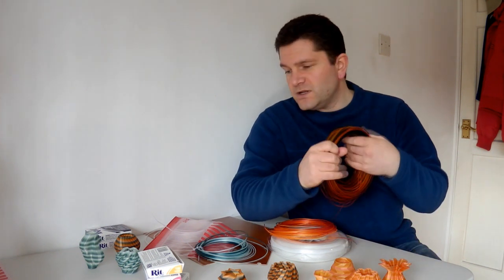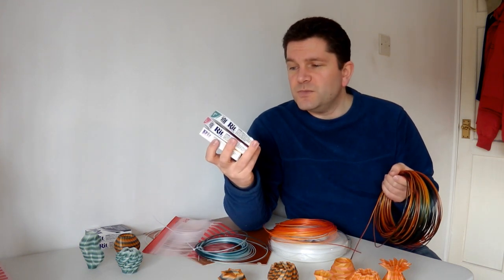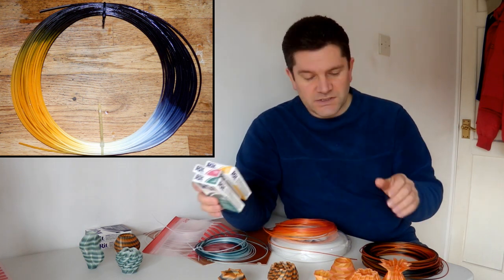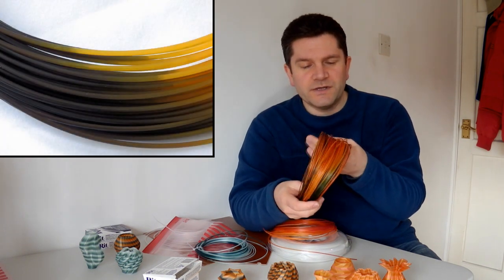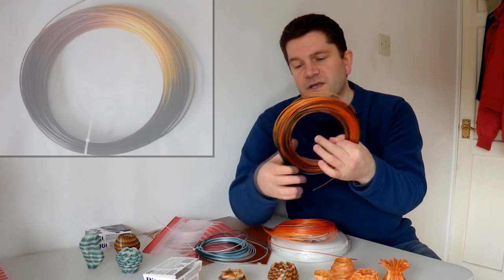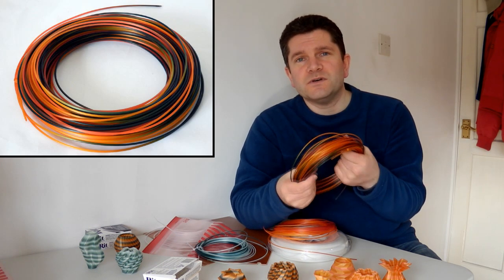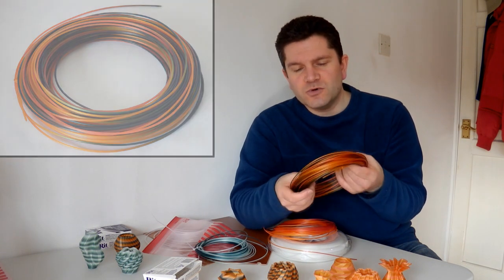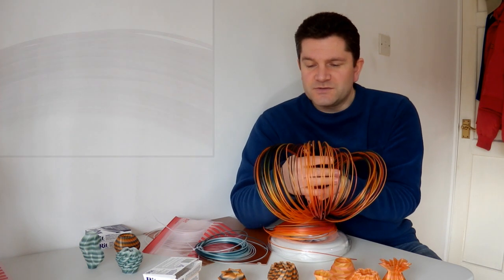The last one I tried with all three colours. Originally I ordered fuchsia, golden yellow, and teal — I was trying to get cyan to produce cyan, magenta, and yellow, but I couldn't get a cyan so I had to use teal. This one was done in three sections: I tie-wrapped off a third and another third, and dyed those in three sections. It only takes about 30 minutes in the bag, then you rinse it in warm water then cold water, and it gives you a really nice dyed effect. I ended up with this one, which is really nice — you've got lighter fuchsias, orange-yellows, and these lovely colour blends.